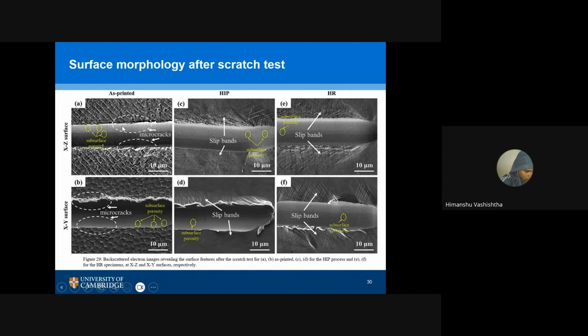Now these SEM images are depicting a pretty good surface morphology of what's happening after the wear test. As you can see, it's showing the highest hardness, and you can see a kind of brittle fracture. A high amount of defects were there, a high amount of dislocations were there, so it's showing kind of a brittle behavior.